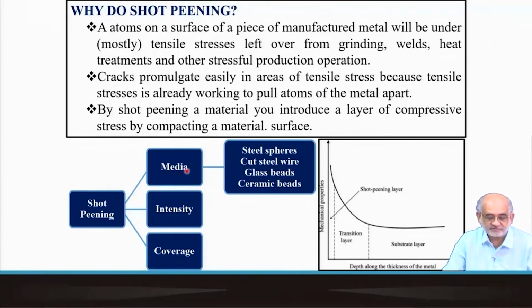So, in shot peening, there are three important components that we have to worry about. What is the media that we are using, what is the intensity or velocity with which it is hitting, which will determine the momentum transfer, and the area coverage, whether we are doing it in a very specific location or over the entire surface. Most importantly, are we able to cover the intended surface region? Let's say this is the surface region we intend to cover. Are we doing it in a localized, inhomogeneous manner or uniformly throughout the surface? These are very important, because unless it is uniform, within that shot peened region a crack may generate and propagate.